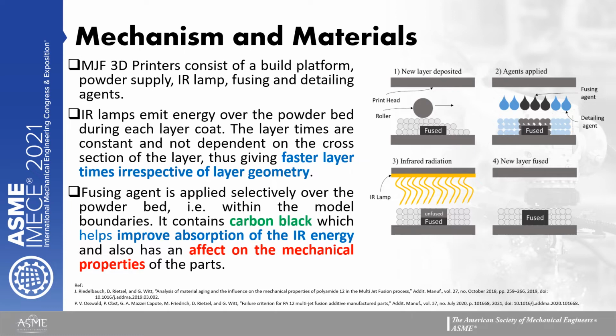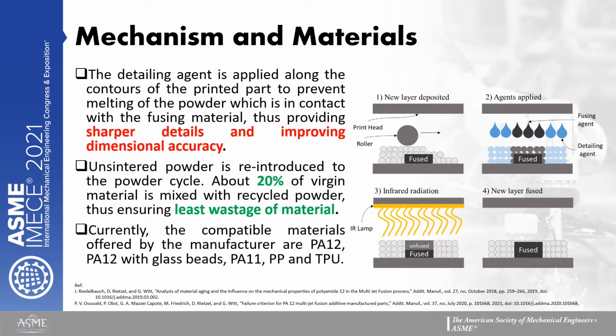Fusing agent is applied selectively over the powder bed, that is, within the model boundaries. It contains carbon black, which helps improve absorption of the infrared energy and also has an effect on the mechanical properties of the part. After that, the detailing agent is applied along the contours of the printed parts to prevent melting of the powder which is in contact with the fusing material, thus providing sharper details and improving dimensional accuracy.